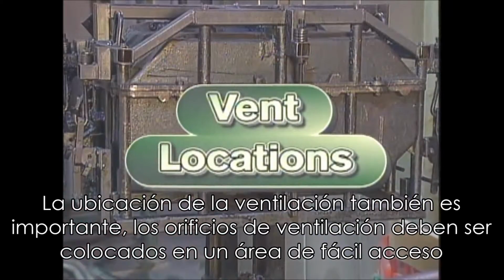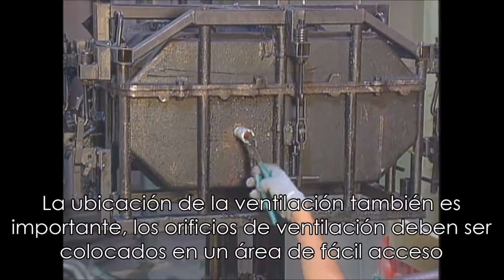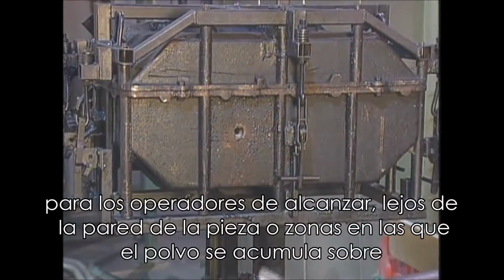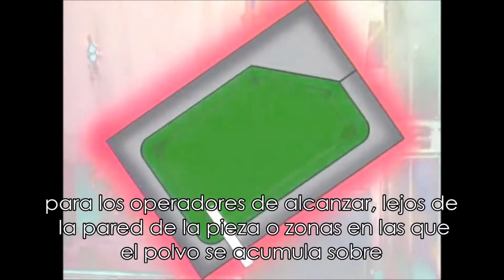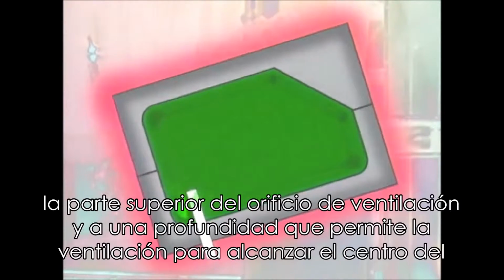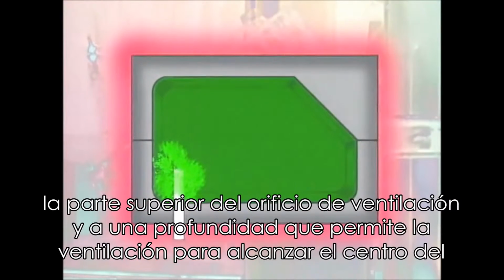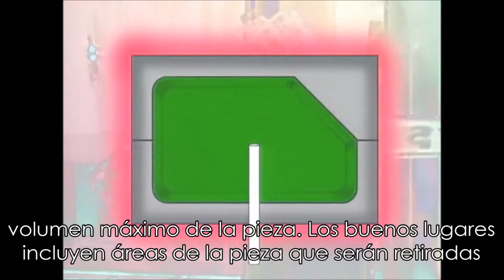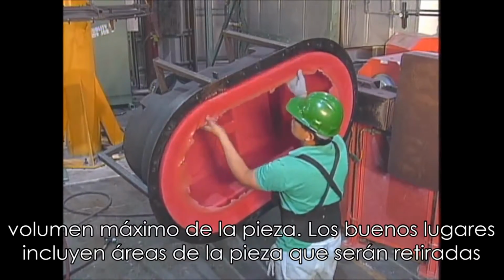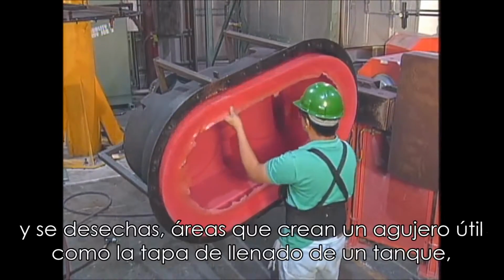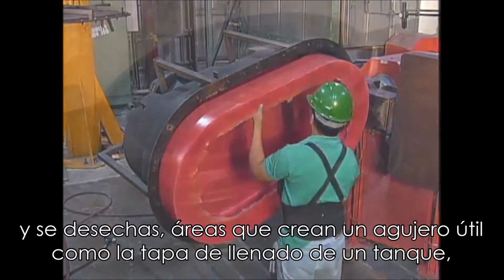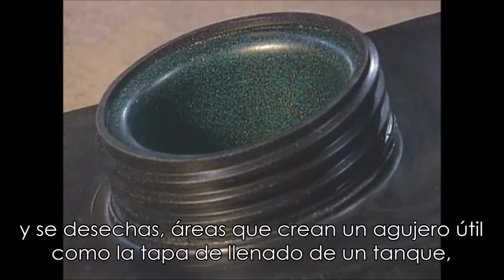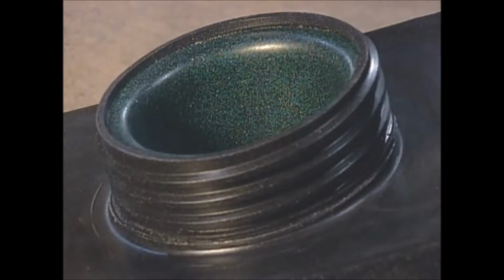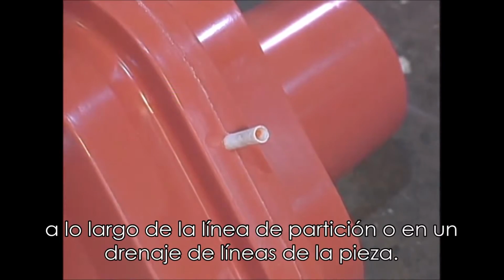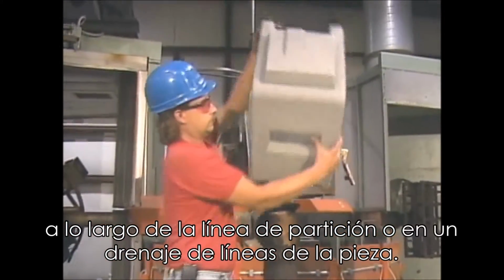Vent location is also important. Vents should be placed in an easily accessible area for operators to reach, away from the wall of the part or areas where powder will build up over the top of the vent, and to a depth that allows the vent to reach the center of the maximum volume of the part. Good locations include areas of the part that will be removed and discarded, areas that create a useful hole, like the fill cap for a tank, along the parting line, or in the line of draw of the part.